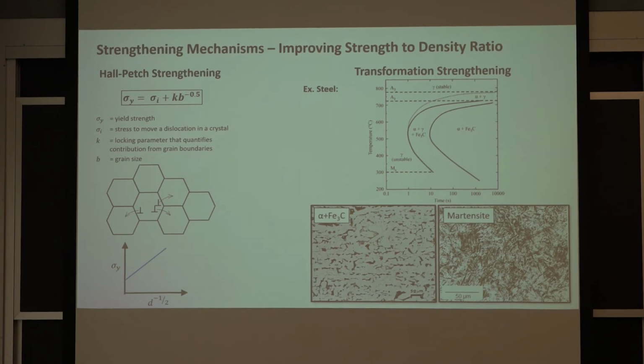When you quench them, some of the microstructure turns to martensite. On the right is what you might have before you solution treated or austenized the material, a microstructure of ferrite and pearlite, where pearlite is ferrite and cementite, also known as iron carbide. When you heat this material up it turns to austenite, and when you quench it, it turns to martensite.